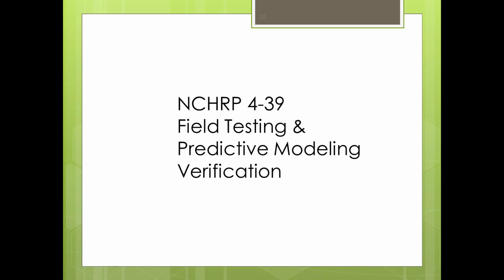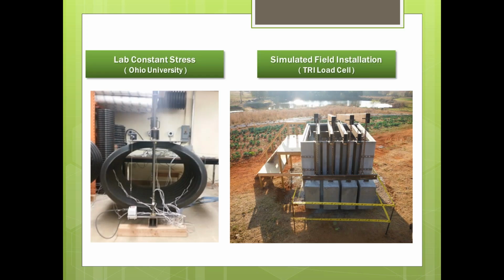And the second phase of the research report itself was really geared around utilizing that test, the UCLS test, and seeing if we can validate its predictive modeling into actual field testing and field verification. This is a bit longer segment of the project. Obviously, real world and full scale pipe testing takes a little bit more time and effort. But really, there were over 75 pipes that were analyzed. There were some done in a lab situation like you see on the left, where they were deflected and strained up to 20% deflection, obviously to accelerate the stress level in the pipe wall and accelerate the stress condition.